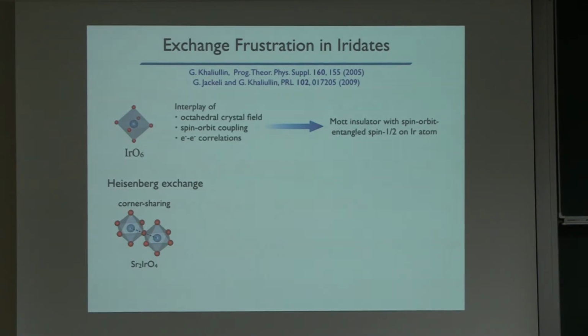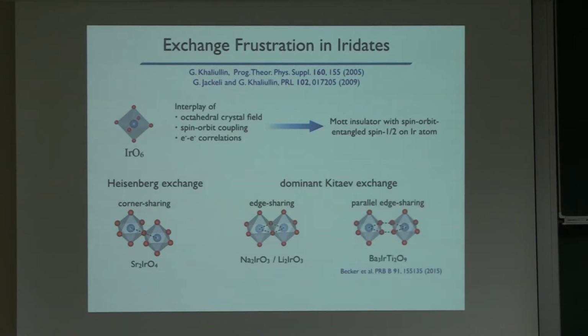So the orbitals, they're d orbitals, they're quite close to the iridium atom, so there's hardly any direct overlap. So most of the exchange interaction goes via the oxygen here. Here, say you have a single exchange path. This single exchange path gives you a Heisenberg interaction if you do the calculation. You can have other microscopic arrangements.